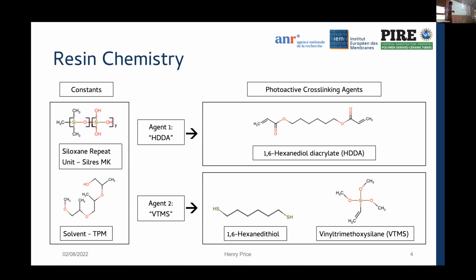So in manipulating the resin chemistry, I don't want to get too into the weeds here with the molecular chemistry, but I had two main variables. I was changing the cross-linking agents, the things that made it photoactive, and keeping constant the pre-ceramic polymer precursor, which was siloxane, as well as a solvent. These affected the end part slightly differently. The main difference is that what I refer to as VTMS, which is an initialism for one of the molecules there, has a greater degree of cross-linking as compared to what I will refer to as HDDA. That's the main difference for all intents and purposes in this project, the degree of cross-linking between these molecules.